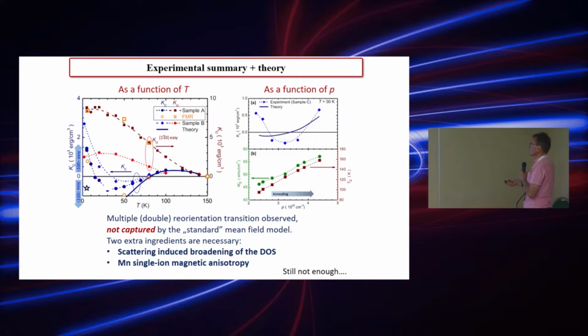Very similar situation when we study it as a function of hole concentration. This can easily be done by annealing. This low temperature annealing is known to increase hole concentration. So we can sequentially anneal one sample and measure, and measure, and measure. And what we established, for example, as a function of annealing, is that the Curie temperature goes up, and this is one of the indications that the hole concentration was indeed going up. And our experimental points for Kc look like that. So we are starting with the as-grown sample with positive cubic anisotropy, then we switch to negative, and then for the maximum annealed sample, we go to positive again. There is a theory which took into account broadening of bands and so on. And the theory, whatever we do, gives only one change of the cubic anisotropy.